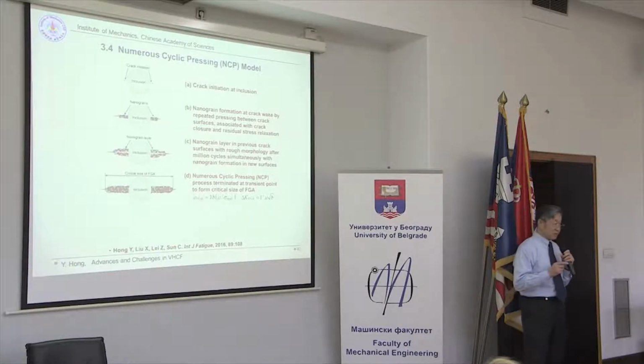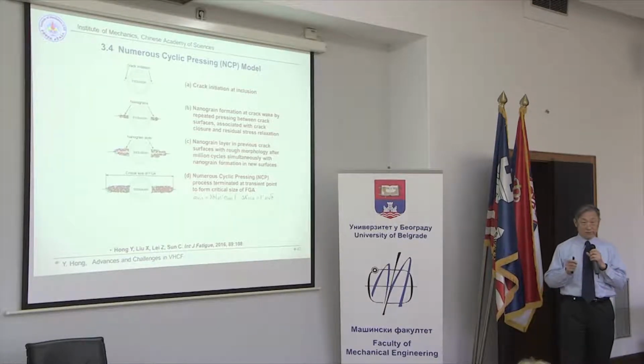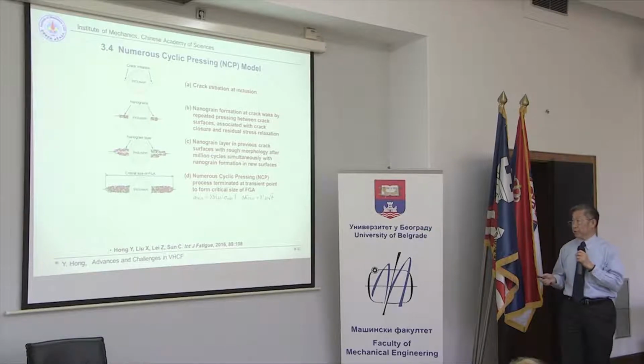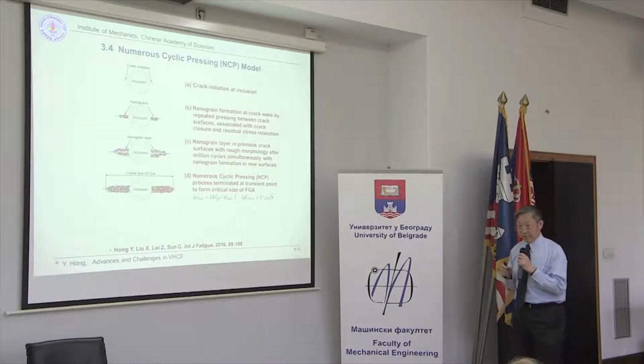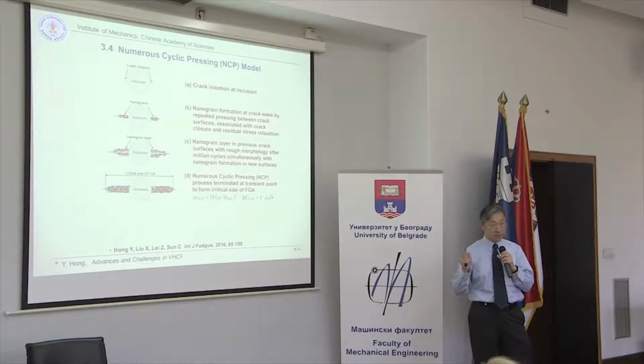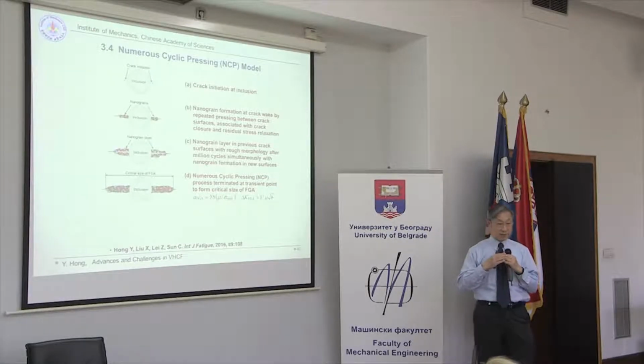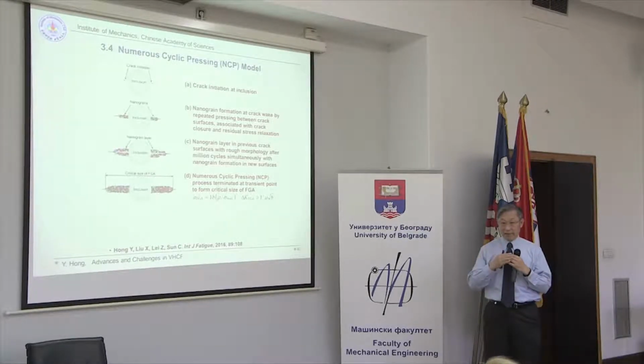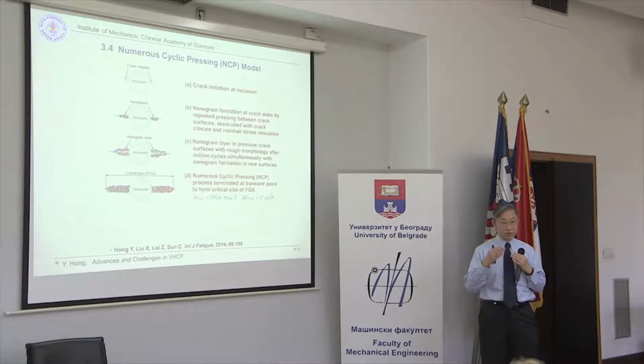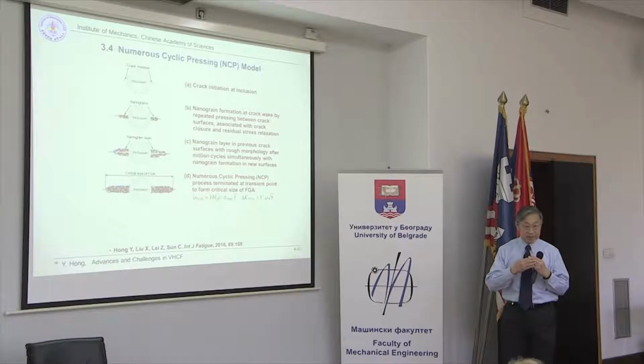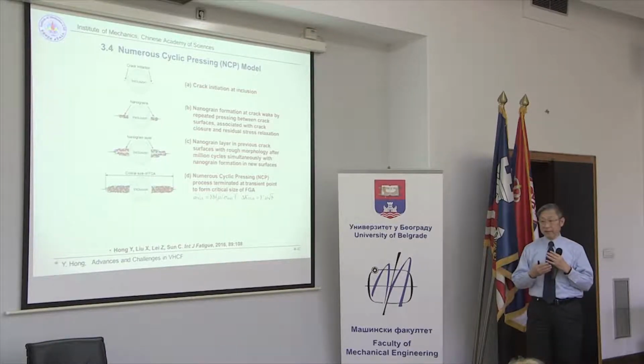So based on such observations of the crack initiation region, we propose a model of numerous cyclic pressing, meaning that a crack will initiate, for the case of high strength steel, from the inclusion, or we may say from the interface between inclusion and the matrix. And after that, the crack surfaces can contact each other due to the crack closure and also the relaxation of residual stress. And this process may happen again and again, due to a large number of cycles.